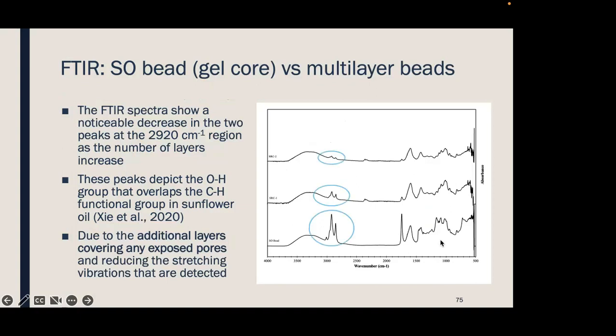I think I'm going to go into the spectra. It does show a noticeable decrease in two of the peaks, namely in this region over here. And these peaks actually depict the OH group that overlaps with the CH group, according to this particular author, due to the additional layers covering any exposed pores. Now, additional layers covering any of these pores are actually detected over here.